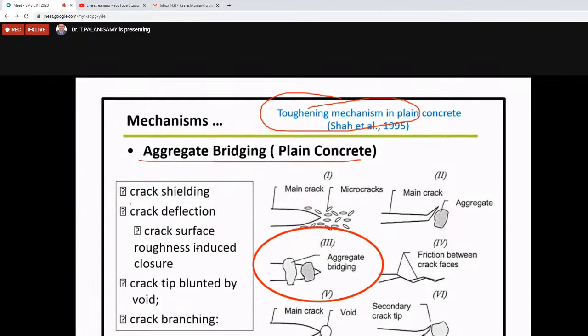For example, there are different stages we can see: aggregate slicing, crack deflection, crack surface roughness induced closure, then crack tip blunting by voids, and crack branching. So these are some of the sub-mechanisms involved in aggregate bridging. What does slicing mean? First a load is applied. What will happen? It tends to slide in this direction. It's like plate tectonic movement. Two plates move together and huge forces act for a long time. What will happen? They may overlap like this, or slice like this.